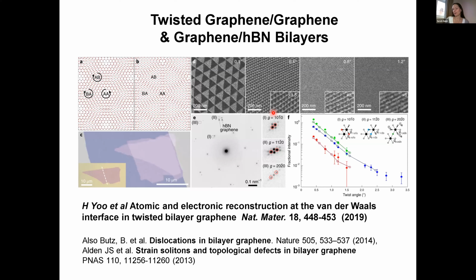And if we just look at what's happening structurally in these systems, when you take one graphene layer and put another graphene layer on top with a small twist angle, that's maybe a degree or less, then we get a reconstruction of the system to produce perfect commensurate stacked lattice separated by these misfit dislocations. And that's what you can see in this image here, which is not my work. This is the work from Yoo et al. in Nature Materials in 2019.